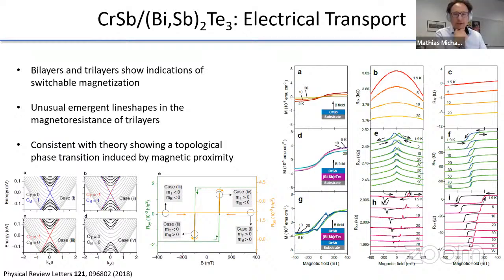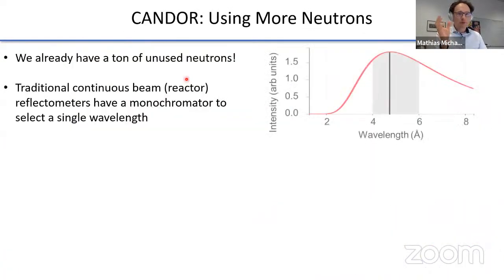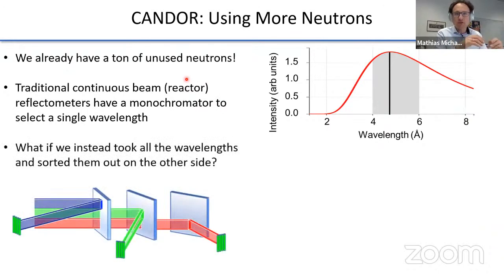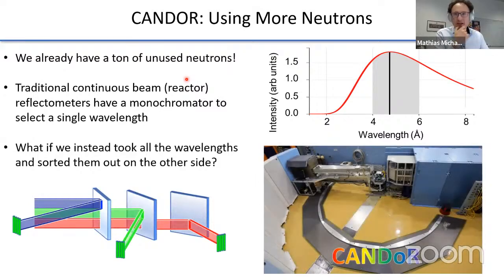Thanks a lot for this super exciting talk. I have a question about this new instrument, CANDOR. Essentially, when you want to use a different window for the wavelength, you get more flux. That's clear. But of course, you lose resolution. It's kind of a trade-off. So you say 2 angstrom is a good window to use, or 1 angstrom, or 1.5 angstrom. How do you choose how much more flux is worth having while not losing the resolution that you get from the broadening?